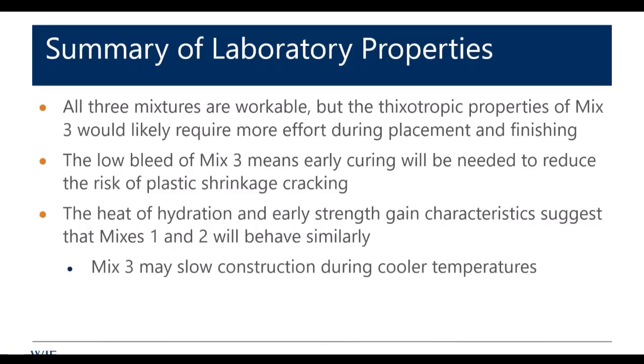The low bleed in 3 makes you pause because you're now thinking of plastic shrinkage cracking and the fact that the setting was highly delayed to get final set. And then the heat of hydration really made it clear that during cold temperature placements, mix 3 could give us some trouble, right? We're not going to get that heat.